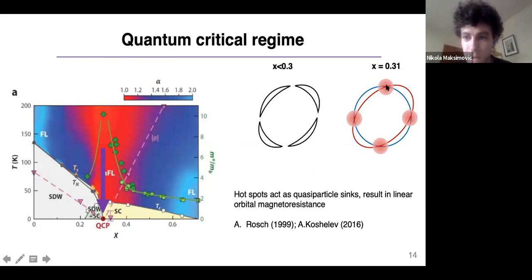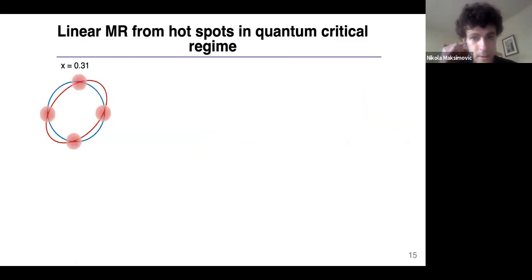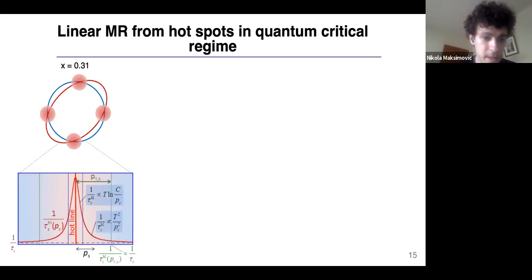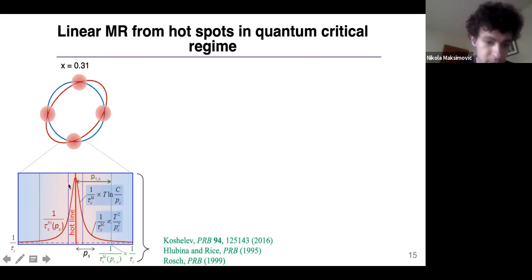But it turns out these regions of very high quasi-particle scattering can also act as quasi-particle sinks. This has been explored by Achim Rosch and Alex Koshelev as well. Actually, Alex Koshelev did this calculation of magnetoresistance specifically for the Fermi surface of Barium-122. What he did is model the scattering rate near this hotspot as a Lorentzian, and the specific parameters of this Lorentzian are dependent on spin susceptibility, as well as the scattering cross-section with these antiferromagnetic fluctuations.